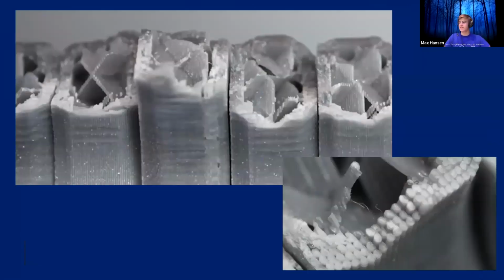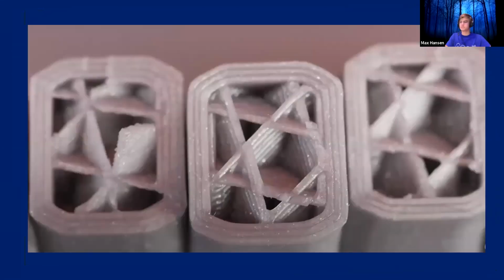So then here you can see this is our XY printing, where they were printed flat. And you can see when it breaks down here in this bottom image, it literally tore through these print fibers, which is the reason why it was so much stronger. It had to rip through each of these individual fibers in order to break the part, instead of, in the next picture here, you can see here it just tore perfectly along a plane. Whatever the weakest plane was in that area, it just ripped the bonds of the plastic straight apart.